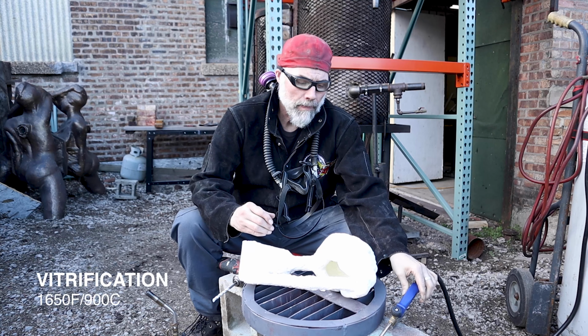And so the key thing is, like I said, to get the gate, the cup, and the vent out in a timely fashion, but also to try to maybe hold off on some of the heat that's going to come off around the shell. We need to get these elements out of the way first before we really attack and try to get the pattern wax out. If we just throw all of our heat up here to the main pattern, I'll guarantee you that the shell is going to crack because the wax doesn't have anywhere to go and it will expand.